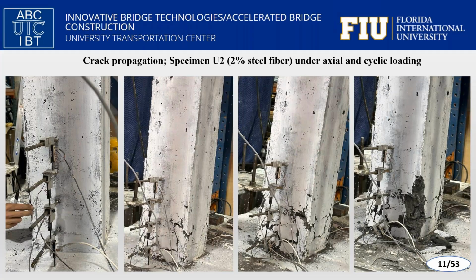We tested another specimen with 2% steel fiber, and the same damage mode was observed. Horizontal and diagonal cracks form under combined bending and shear forces, intersecting with the flexural cracks. The steel fiber delays crack propagation and prevents rapid deterioration.